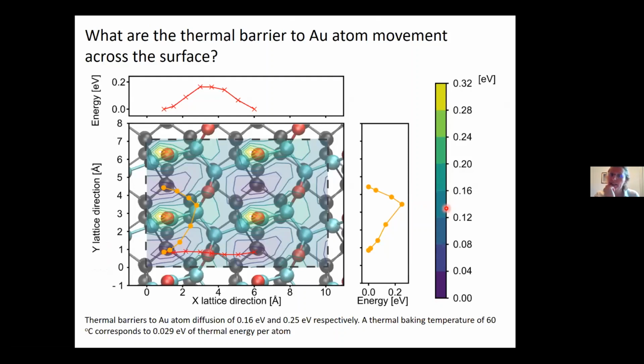One of the things we also asked our DFT colleagues to think about is, can a single atom, just by virtue of the thermal energy of the system, move around? We asked them to look at energy barriers on the surface, because in one of our steps in the TEM, you actually do a thermal bake. So you slightly elevate the temperature of the system, and again, we wanted to be sure that that temperature elevation wasn't causing an effect on anything we see moving. From the DFT simulations coming out at the moment, the thermal barriers for atom movement seem to be too high for thermal motion at room temperature to be a concern. So we've checked the electron beam isn't moving the atoms, and we believe from the DFT and some follow-up electron microscopy experiments that the thermal energy of the system is not going to move them around.